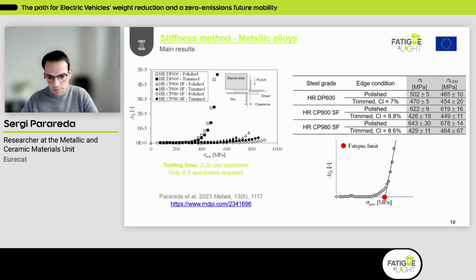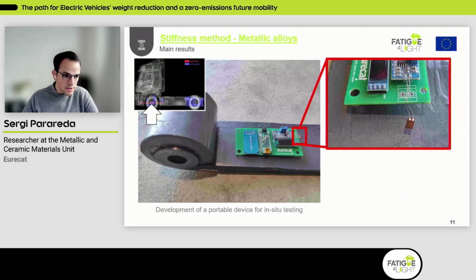And here, once again, the comparison between the fatigue resistance obtained by the stiffness method and also from the staircase method. And well, just to mention that we can obtain this data by using 2 or 3 specimens. And here also, another point that we are working on is to not only get the data at the specimen level. So the next step is to obtain the data directly from the real components. So here you can see a front leaf spring from a truck.